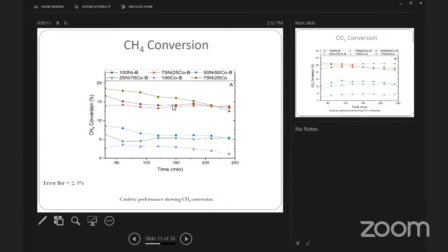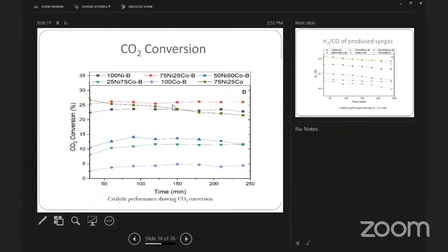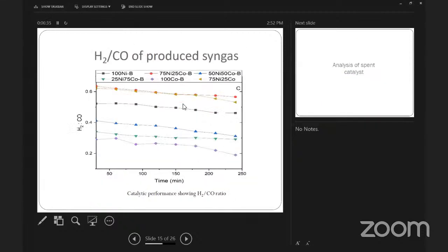has more conversion, not CH4 here, but CO2 conversion. In CO2 conversion, we can see the bimetallic catalyst performing better compared to the monometallic catalyst. But here also the decline in conversion is higher compared to the non-boron catalyst. Also, in the production of syngas, we got around 0.7. We also compared it with the non-boron catalyst and other bimetallic catalyst, and we can see there's a smaller decline.